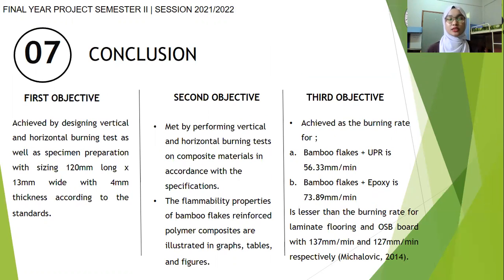The first objective is achieved by designing a vertical and horizontal burning test and also specimen preparation according to the standards. And the second objective is met by performing a vertical and horizontal burning test on the composite material in accordance with the specification, and the flammability properties are illustrated in a graph, table, and figure. As for the third objective, it is achieved as the burning rate of both composite materials, A and B, as you can see there, is lesser than the burning rate for laminate flooring and OSB board.